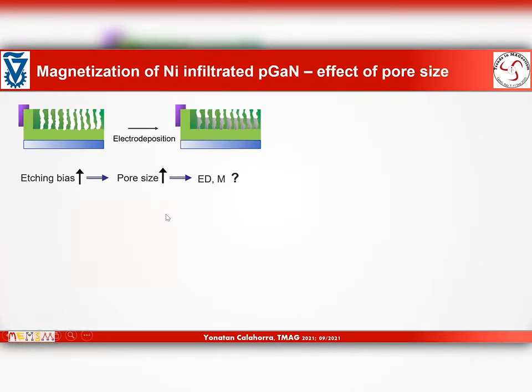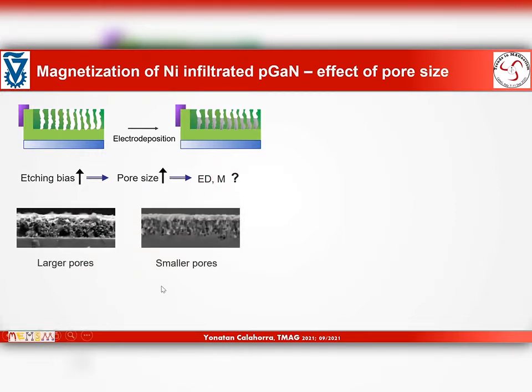Let's see some of the results. First, we can look at the effect of pore size. Our process was calibrated such that we knew how to control the pore size by, for example, increasing the etching bias during etching. And then the question is, how will that affect electrodeposition, and how will that then affect magnetization? So we see 2 samples with different pores. We have larger pores with higher etching biases and smaller pores.